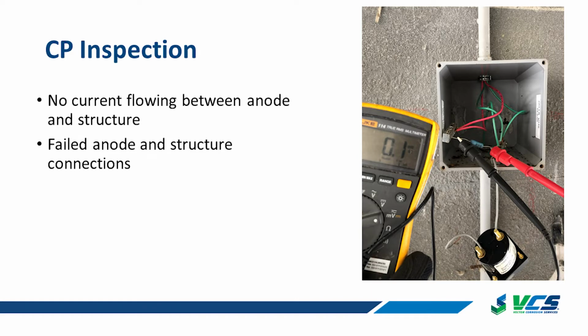So obviously, I showed that amp meter. We got our actual meters out, and unfortunately, when we came to site 15 years after installation, there was no current flowing between any of the anodes on Pier 3 or 4. Inspection of the system identified that most of the anode and structure connections had failed because they just weren't properly connected and durable for a 15-year service life. So some issues on the initial installation affected durability. Those things can be picked up if you're monitoring and maintaining a system, but unfortunately that wasn't done in this situation.